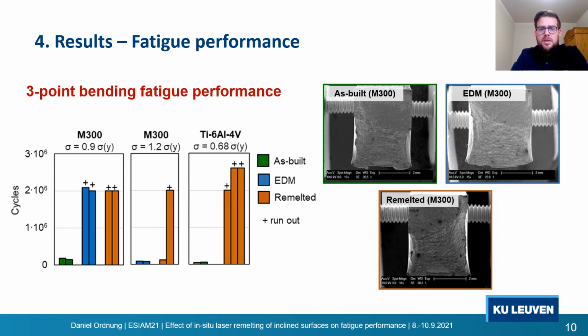The significant improvement of the fatigue performance in 3-point bending test of the remelted samples can be on the one hand explained by the surface roughness reduction. But on the other hand, if we look at EDM samples and remelted samples, we see that the remelted samples performed much better in the fatigue bending tests, even though they have a higher surface roughness. So this clearly indicates that not only the surface roughness reduction, but also other factors are beneficially impacted by the laser remelting process. One explanation could be connected to the modification of the subsurface microstructure. Here it needs to be investigated further if the laser remelting, for example, induces compressive stresses which have a positive impact on fatigue performance.